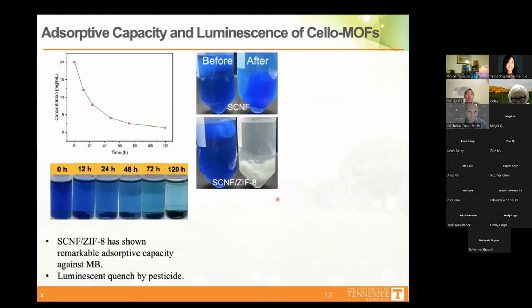Okay, so the next question is how can we use this material? The first thing we tested is whether we can use it to absorb chemicals like pollutants, dyes. So here is methylene blue, and we dissolve it in the water, and you can tell this dark blue color right here. And then we measure the methylene blue concentration against different time. We throw the MOF cellulose hybrid into this liquid and let it absorb, and it turned out it has really good absorption capacity.